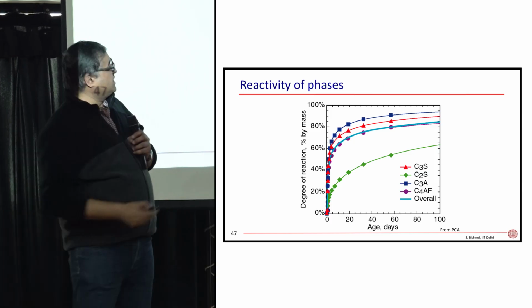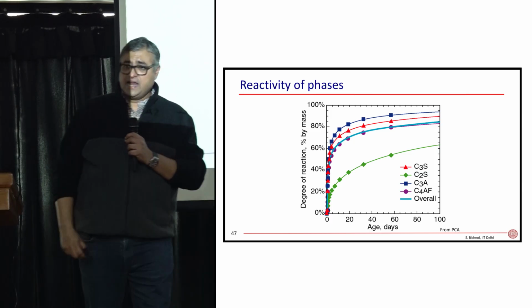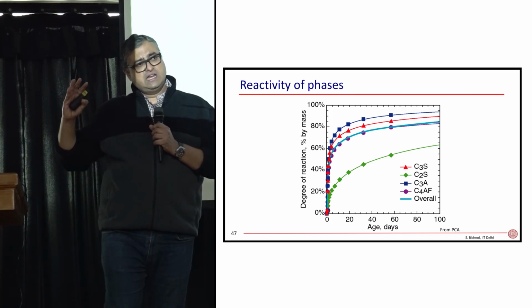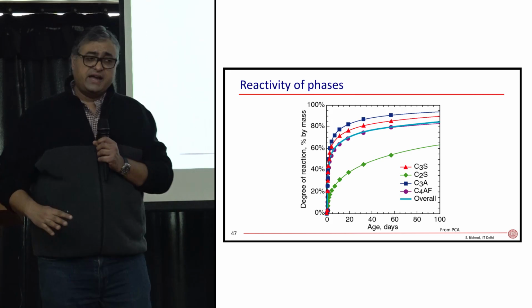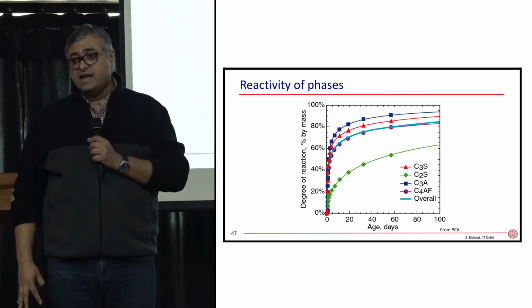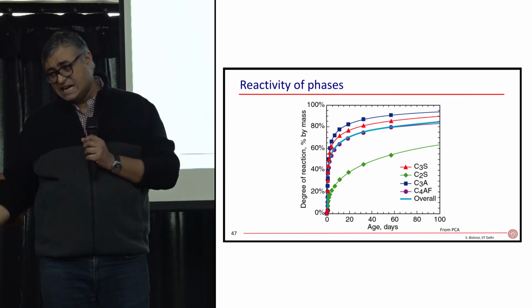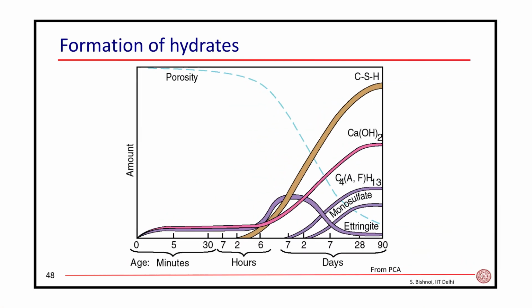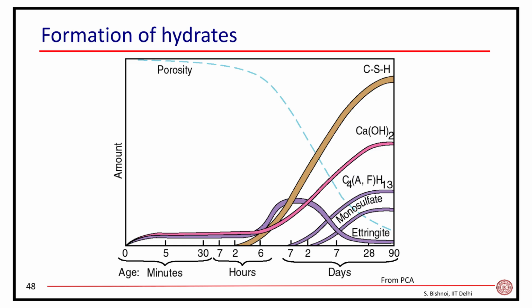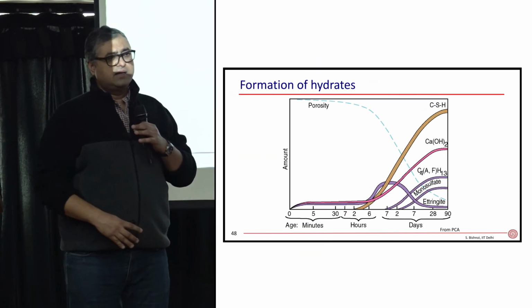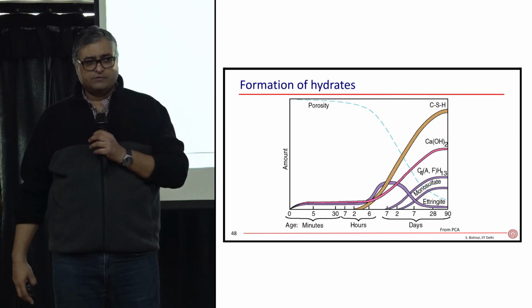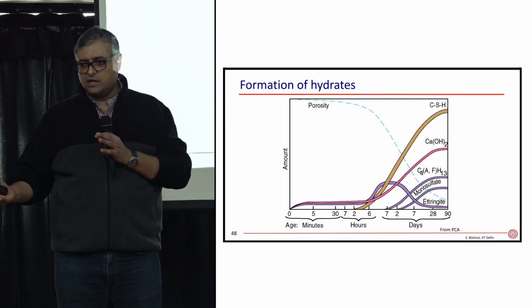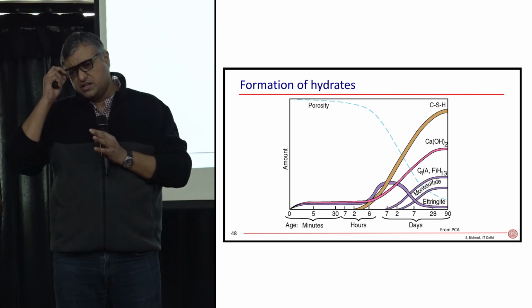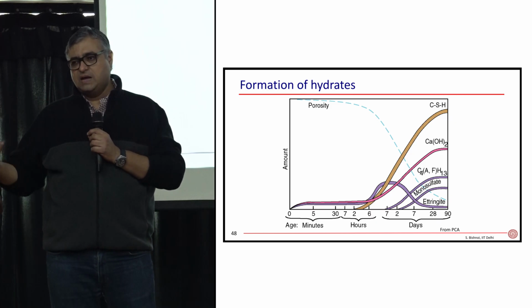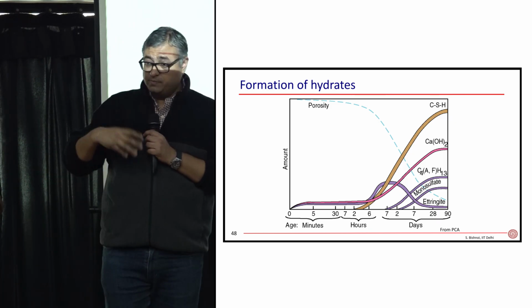The dissolution slows down. Once your aluminate and alite hydration slow down, there's very little C3S and C3A left. Only then can the other two phases really start to dissolve and react properly. That's why they react later, because they have these common ions in them. So the rates of reaction of all of these things are different. That's why some people say that C3A and C3S contribute to the early strength and C2S contributes to the long-term strength of concrete. Yes, it's partially true, but everything is reacting all the time. Everything is contributing at all the ages. But yes, it is true that if you have more alite present, you'll have a higher strength increase in the early age than in the longer term.